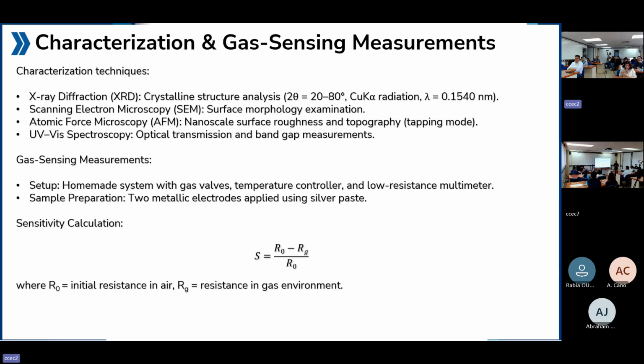Once all the characterization was done, these materials were used for gas sensing measurement, where a homemade setup was used, which had gas inlet valves, 2 tanks of gases, that is carbon monoxide and propane, a low resistance multimeter, a temperature and pressure controller, and silver paint, which acts as an electrode. Once the measurement was taken, sensitivity was calculated with the formula (R0 minus Rg) by R0, where R0 and Rg are the resistance in air and the resistance in gas, respectively.